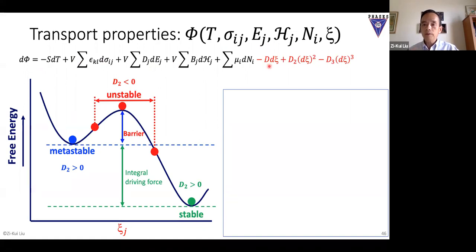The first derivative gives us the driving force. This means this point is stable, this is stable, and this is unstable - these are all equilibrium points because the derivative equals zero, but two are stable and one is unstable. That's the first term. Then the second term talks about stability - the second term here is all positive, so it's stable.